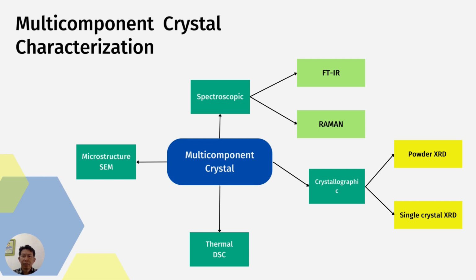Characterization of solid state properties is performed to confirm whether the multi-component crystal phase was successfully formed or not by some instruments. Crystallographic properties by X-ray diffraction, powder and single crystal. Thermal and thermodynamic properties by DSC, DTA, and TGA analysis. Spectroscopic analysis to evaluate the intermolecular interaction of functional groups in the multi-component crystal, and also microscopic analysis by SEM and polarization microscope to investigate habit and crystal size of the multi-component crystal.